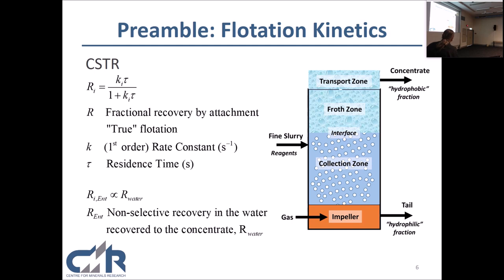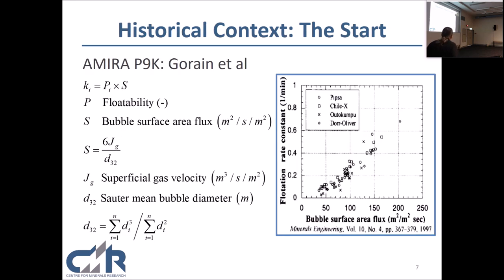And I'm not going to put a specific form in here, but there are a variety in the literature, but all of them would say that, yes, there's material that's recovered by attachment to the bubbles. In other words, we call that true flotation, but there's also material that is entrained, dragged with the water, that is non-selectively recovered, in some proportion to the recovery of water.